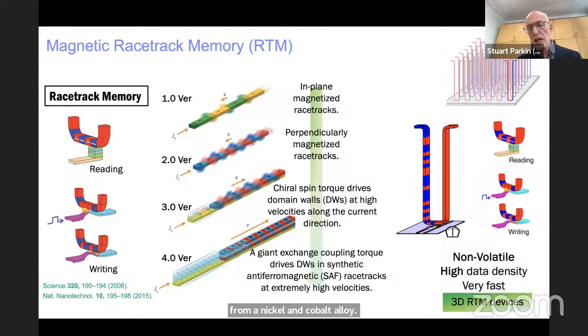However, those types of materials have no anisotropy, so the domain walls are very large, hundreds of nanometers, and indeed they're highly flexible. They can extend over microns. So this is not good. So we switched to instead multi-layers formed from cobalt and nickel. And those multi-layers, the interfaces, give rise to a strong perpendicular magnetic anisotropy.